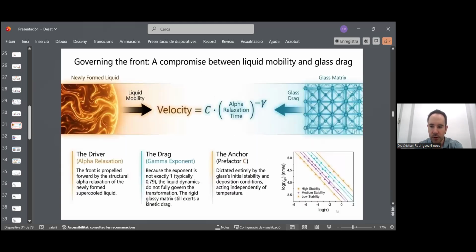Okay, so here we plot this velocity of propagation as a function of the relaxation time of the superheated liquid, and we see some change depending on the stability of the glass. This is the more stable glass, so the velocity is lower for a given temperature. In the case of the less stable glass, this front propagates at a larger velocity.